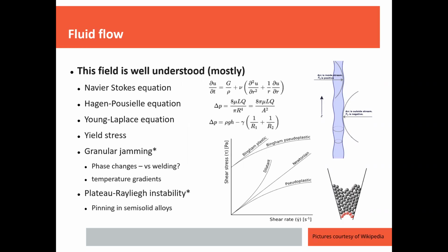Granular jamming as well is for semi-solid metals not very well understood, I would say. Now, in a semi-solid metal, as you're extruding this thing, it's cooling down, it's going out of the nozzle, and your particles are growing in size and sintering together. And the active growth in the size of the particles exacerbates granular jamming.